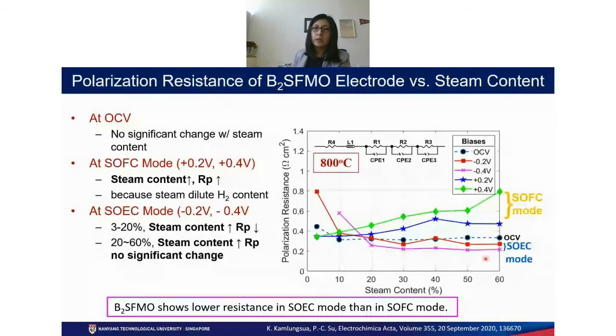And for the SOEC, this red and pink curve, it stays high in the beginning, and then after 20-30% it starts to stabilize. Okay, meaning that more moisture does not really get taken up by the electrode. Okay, and another important message here is that when you use SFMO in SOFC mode and SOEC mode, the impedance is lower under the SOEC mode, which implies that perhaps this material is more suitable to operate under SOEC mode than the SOFC mode.